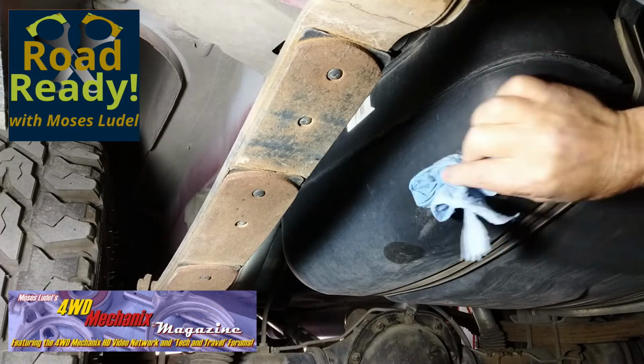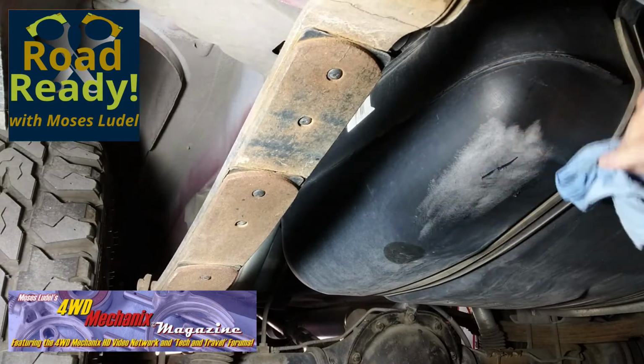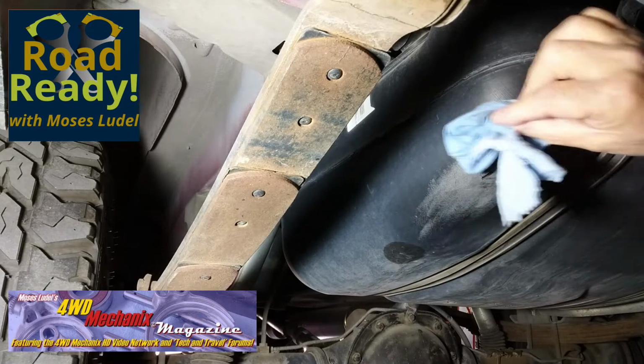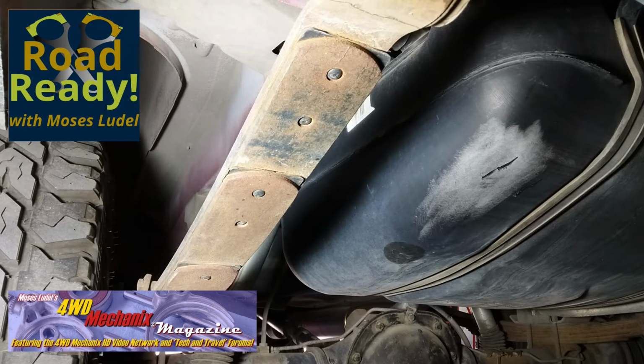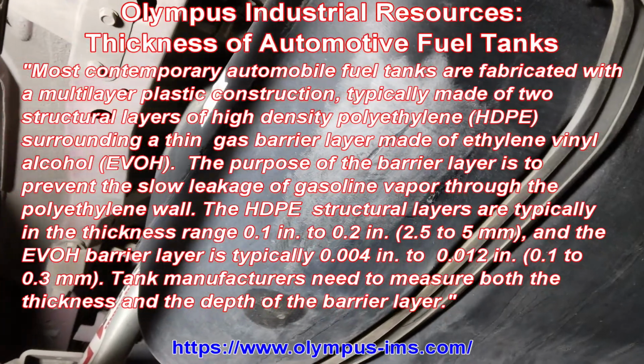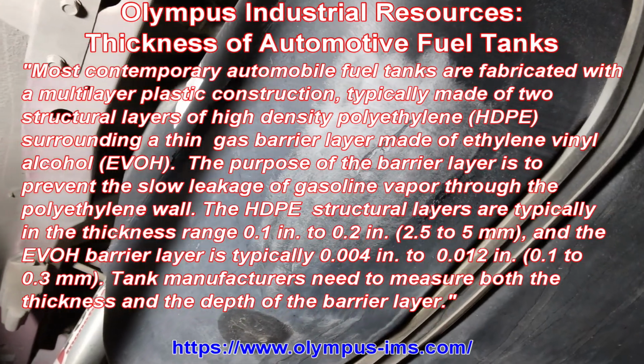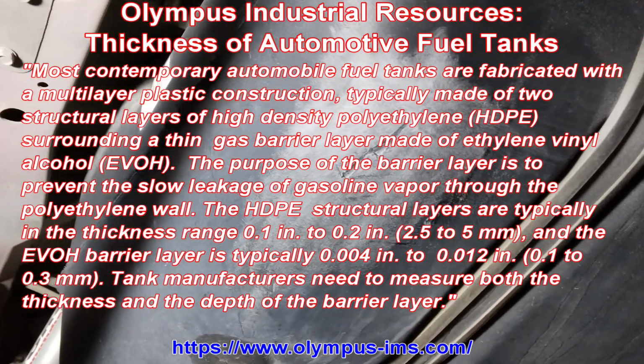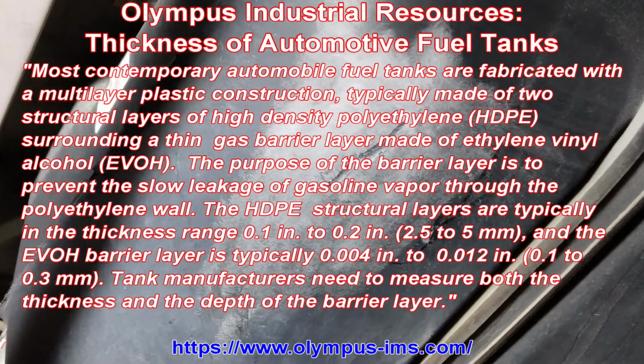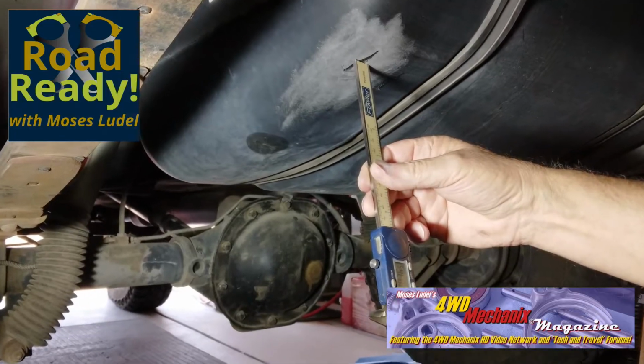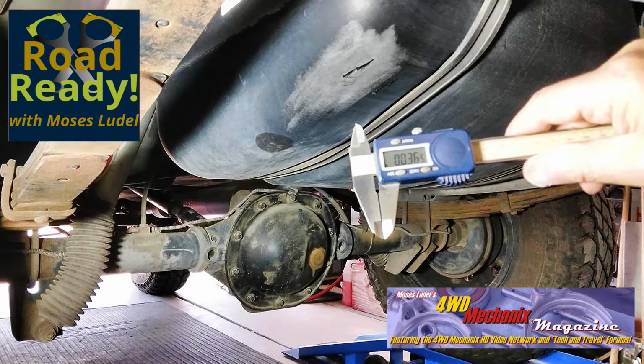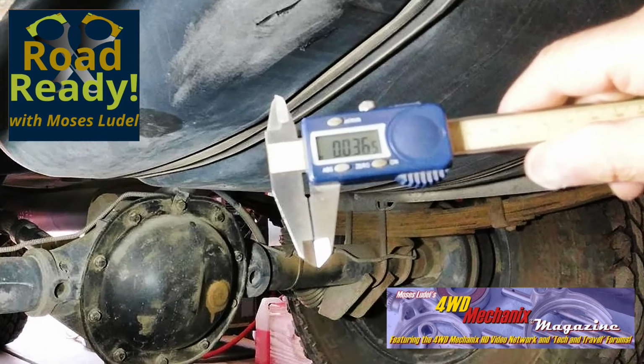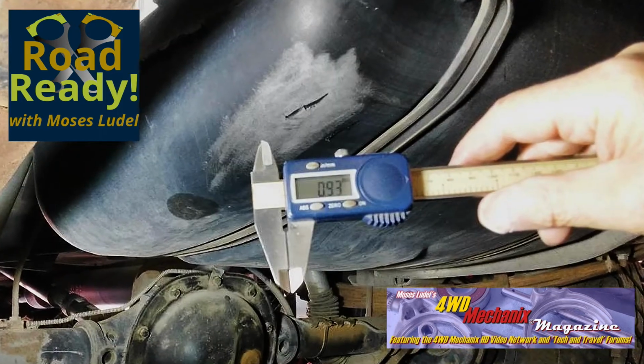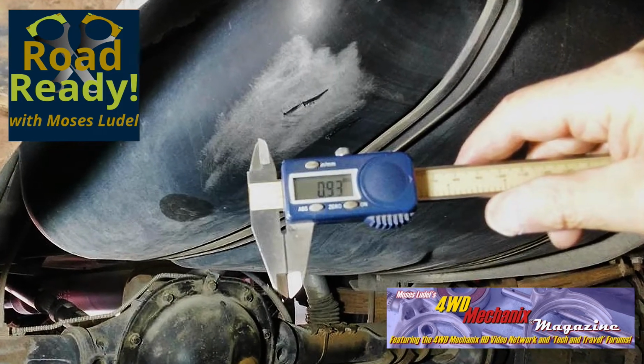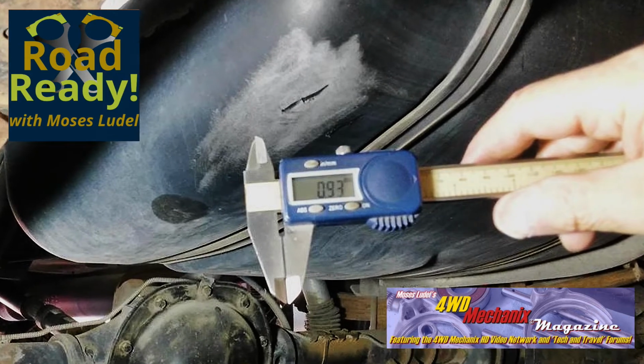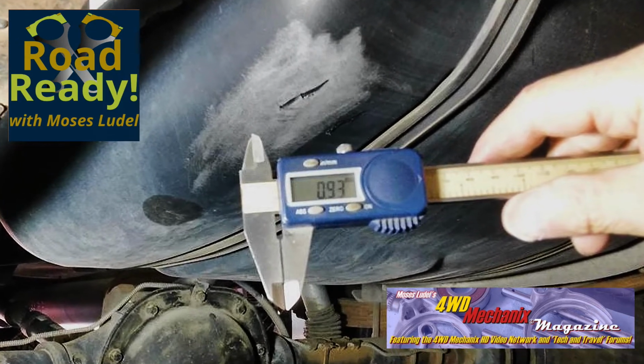We now have a clear sense for the extent of the damage. We'll get a precise measurement of the depth of the scrape. Here's some perspective on how the scrape affects the thickness of the tank. We thank Olympus Industrial Resources for this information. At the deepest point, it is 36 thousandths of an inch, or 0.93 millimeters. If this tank is only 2.5 millimeters thick, and 0.93 of that is a scrape, we don't have much material left.